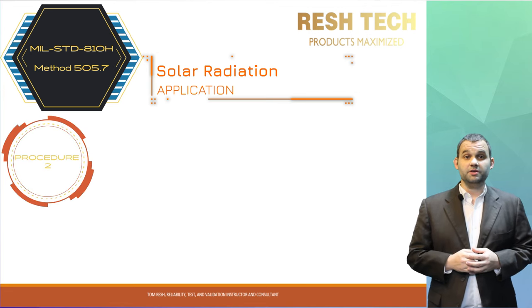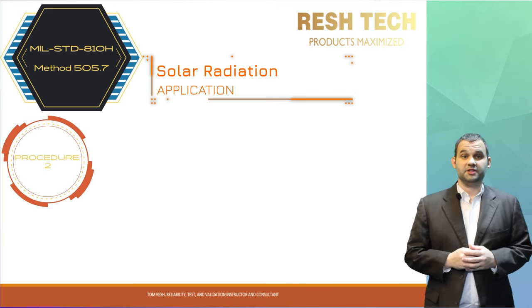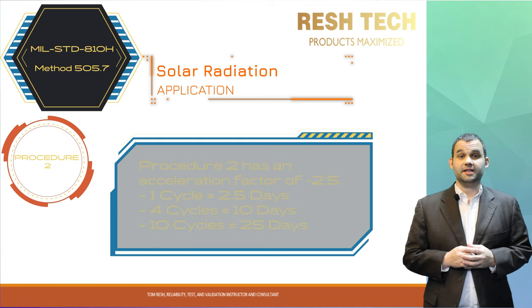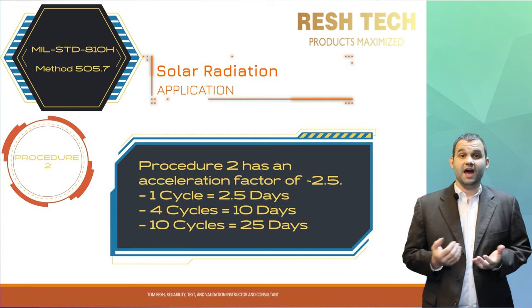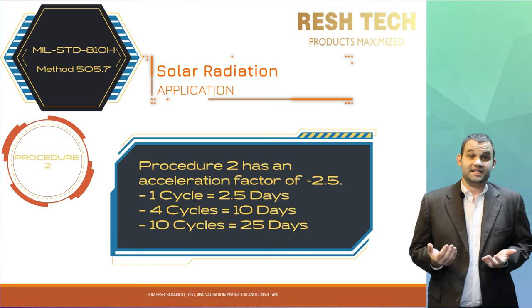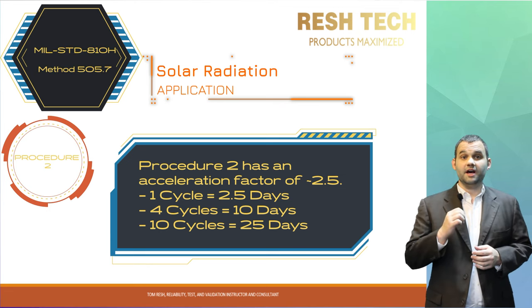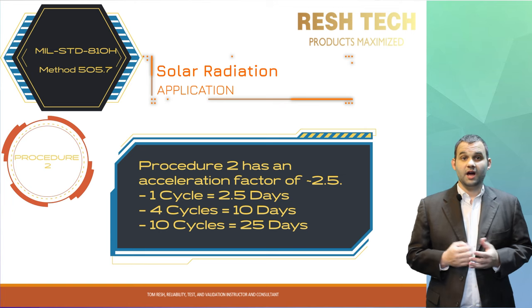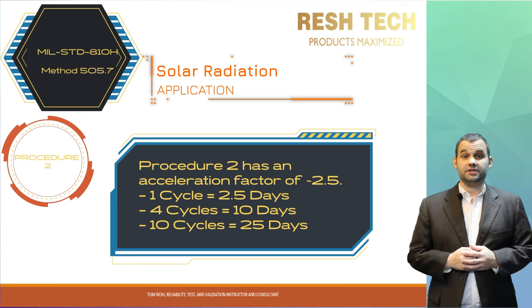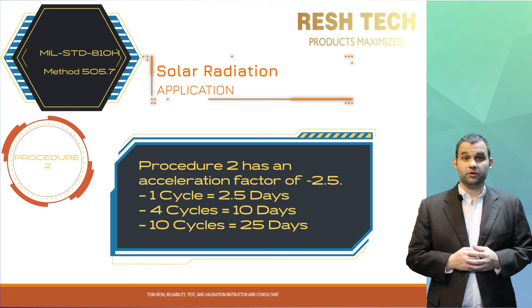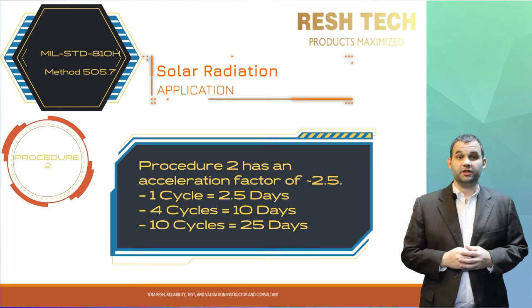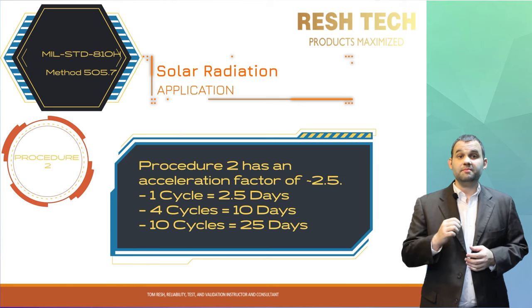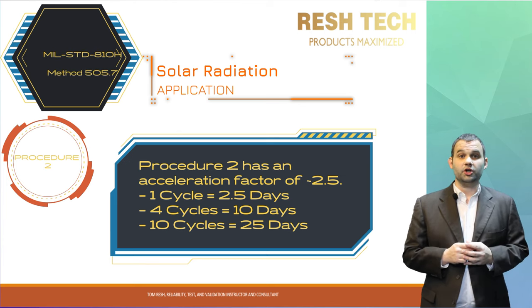Let's jump into Procedure 2 now. A cool tidbit of information is that Procedure 2 has an acceleration factor of approximately 2.5 as far as the total energy received by the test item is concerned. In other words, one 24-hour cycle, as shown previously in Figure 505.7-2, produces an acceleration factor of 2.5 times the solar energy experienced in one 24-hour diurnal cycle, plus a 4-hour period with the spectral lamps turned off to simulate the thermal cycling and stresses that would occur after the sun has set and your system starts to cool down.